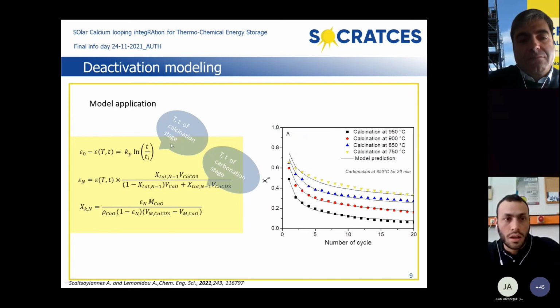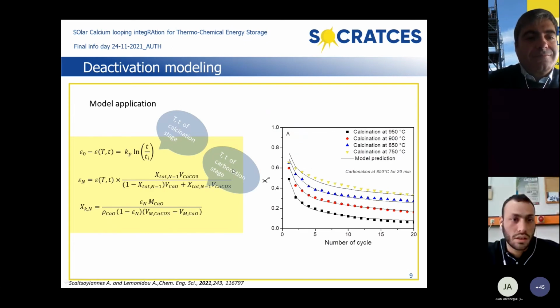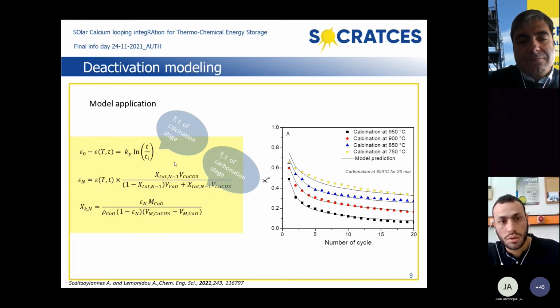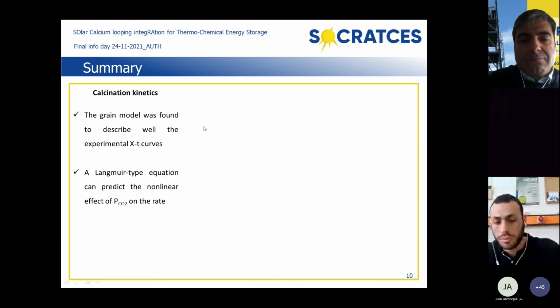For these experimental results, these were translated to mathematical equations, and a non-empirical deactivation model is developed, where parameters such as temperature and time of each step of calcination and carbonation are introduced. And you can see here how the model, the solid lines, predict very well the experimental result for deactivation under different conditions.